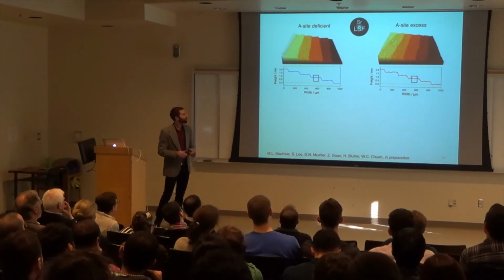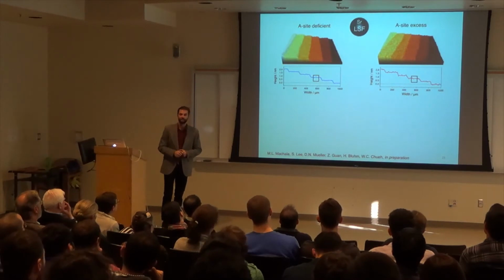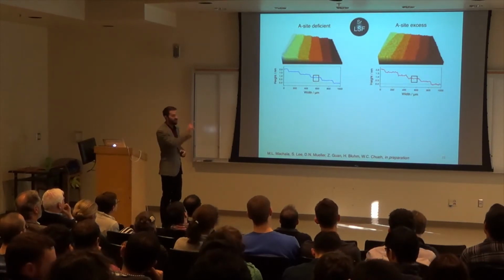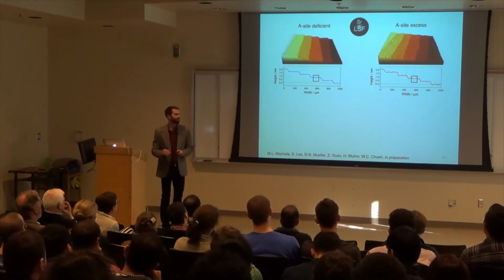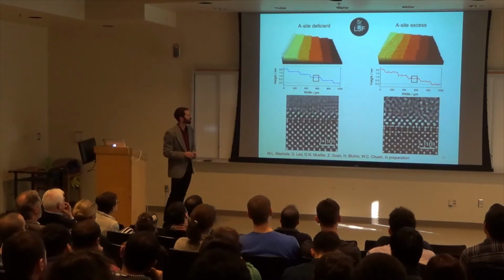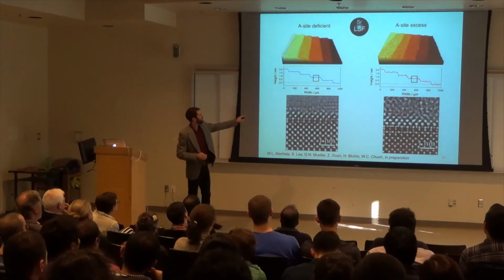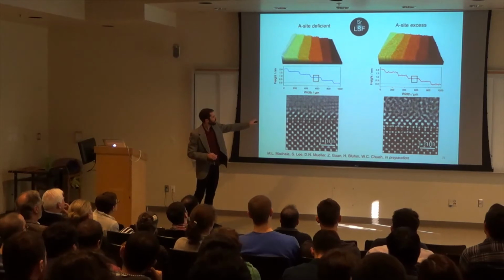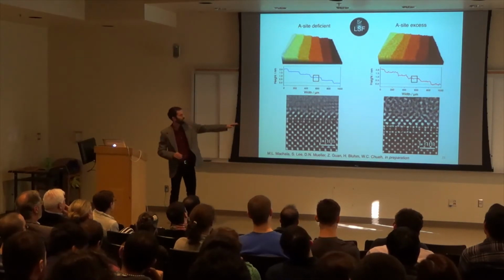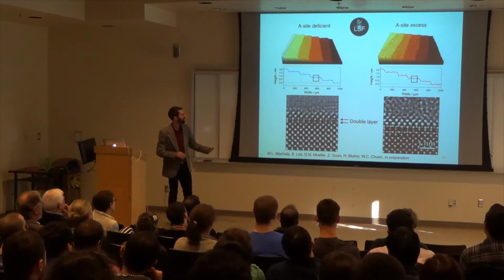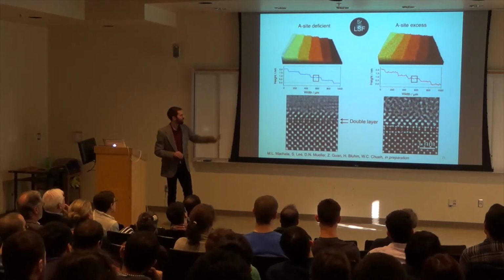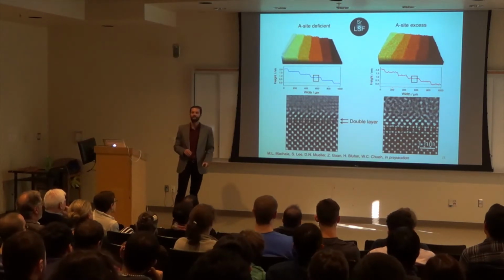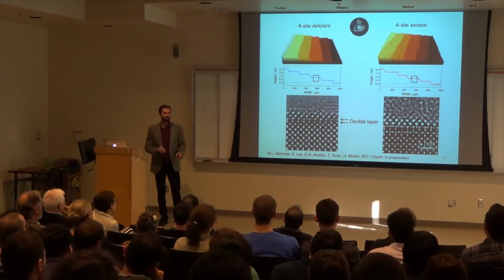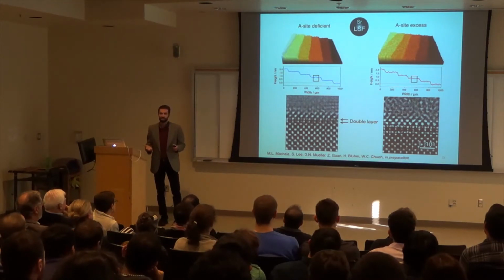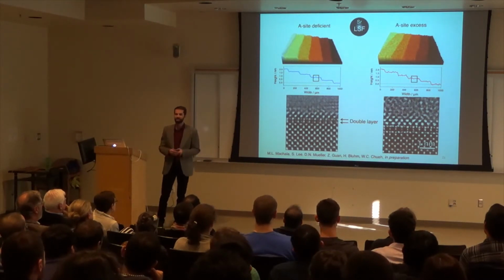Now, we use high-resolution transmission electron microscopy to zoom into the surface to see if we can see any structural changes here. That's what it looks like. On the one with less of the A site, we can see a very distinct difference from the other side, the A site excess. And I'm going to highlight that right here. You can see the formation of a cation double layer. Now, we see something structurally different. But what is chemically found at the surface?